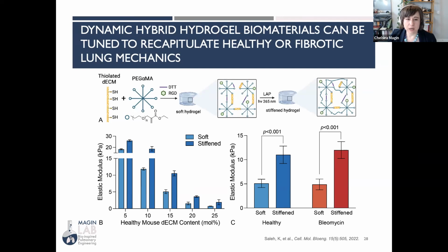So first, we use a chemical reaction to treat the decellularized extracellular matrix molecules, and we convert the primary amines on these proteins into thiol molecules. These thiols can react with our polyethylene glycol alpha methacrylate molecule. If anyone is a chemistry nerd, you'll note that this alpha methacrylate is connected to the PEG backbone on the opposite side of the alpha carbon. This allows the molecule to degrade by releasing this small alcohol group and not breaking the backbone of the polymer. So our polymer is stable over at least 60 days in cell culture, which allows us to run long-term models